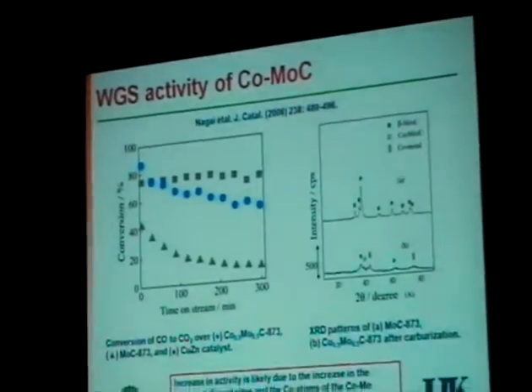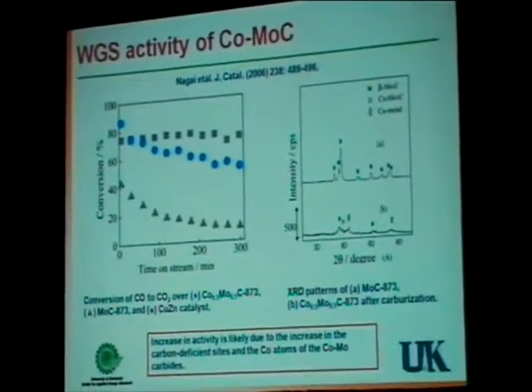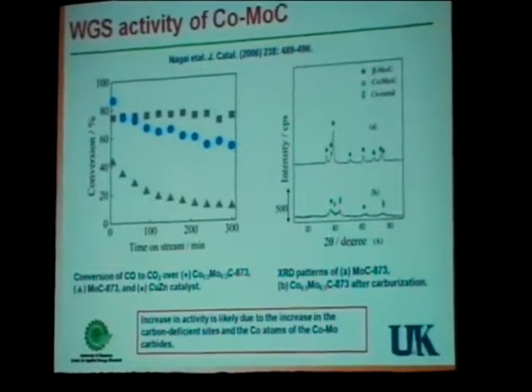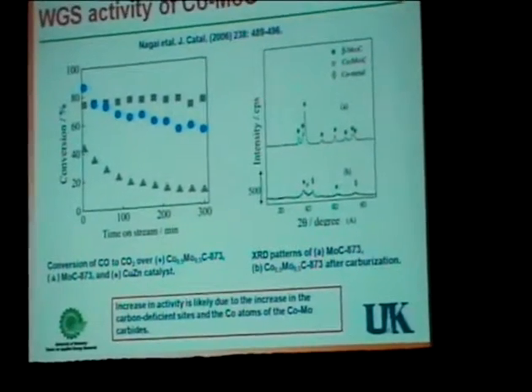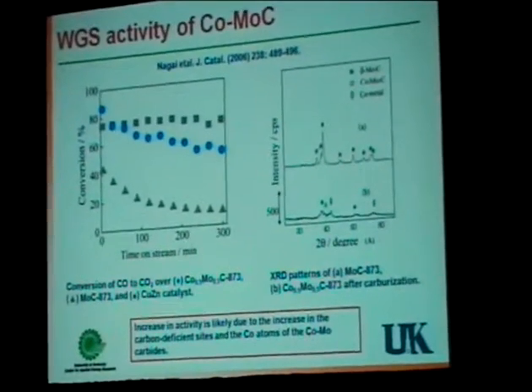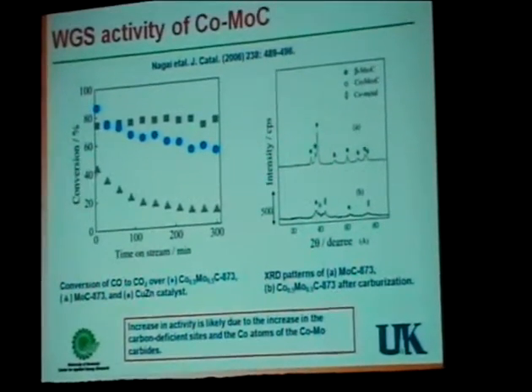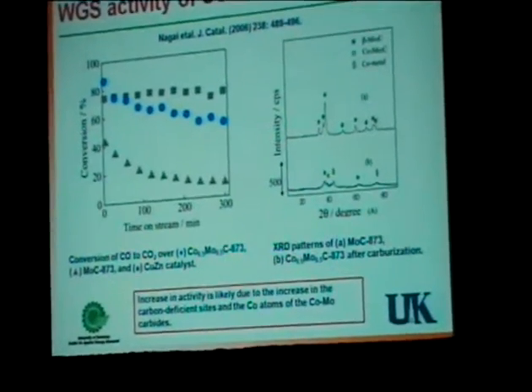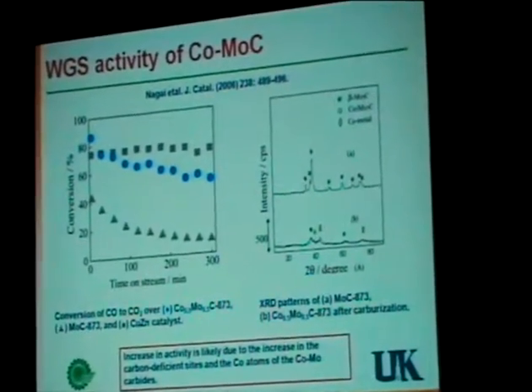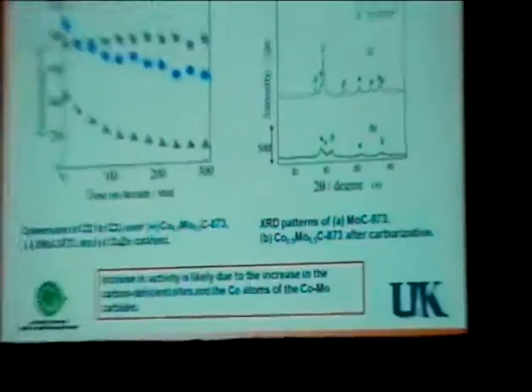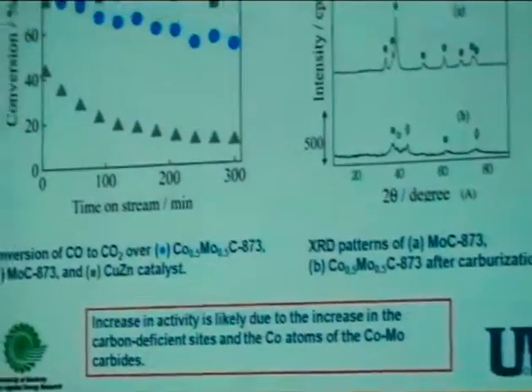When you don't have any cobalt in it, the catalyst deactivates by almost 50%, whereas the cobalt-added catalyst shows steady activity, but there is some initial deactivation there. It seems that the molybdenum carbide, if you promote it with the cobalt, shows a reasonable activity, and it is comparable with the present catalyst.